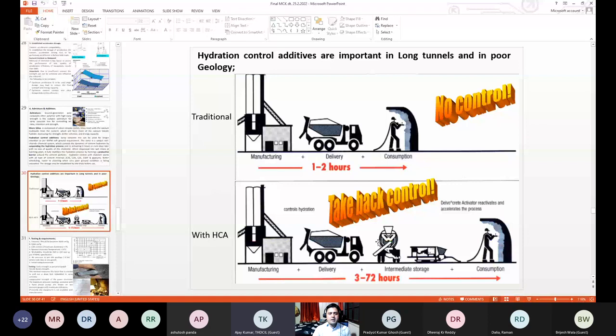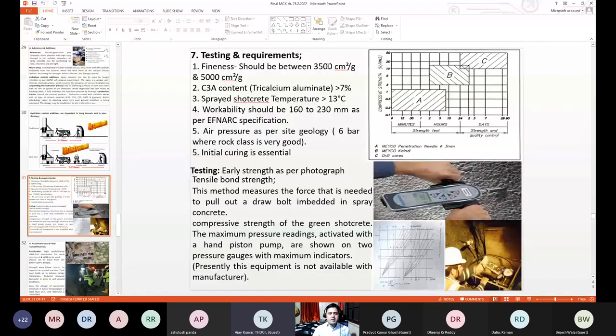Now I'm on testing and requirements. Fineness should be between 3,500 to 5,000 square centimeters per gram for cement. C3A content should be more than 7%. Spray shotcrete temperature should be more than 13 degrees centigrade. Workability should be 160 to 230 mm as per EFNARC.